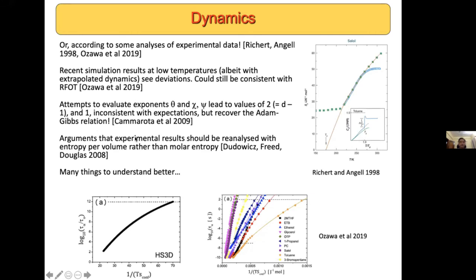On the other hand, some recent work where equilibrium simulations have been done below the mode coupling TC, and dynamical relaxation times have been inferred from extrapolation, seem to suggest that the Adam-Gibbs relation doesn't work so well in simulations. And the colleagues involved with this work, Ozawa and company, also went back and looked at experimental data, which they show here in the bottom right figure, which seems to suggest that in fact it doesn't work.